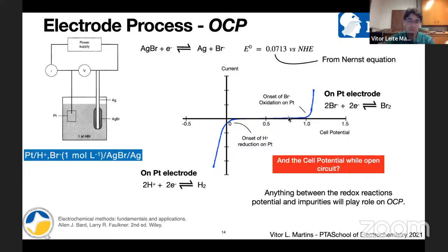So it could assume any value here because the platinum electrode has no equilibrium reaction on its surface. So it could measure anything. Could it measure something around here? No, because for the potential to be in this region, we need electrons to flow, and we are not applying anything. We're just measuring the potential while the cell is open. Could it be here? No, because there's a reaction occurring here too. So it will be any value in this range here, and will probably be due to some impurities like oxygen or some impurities in the salts that you used, something like that.